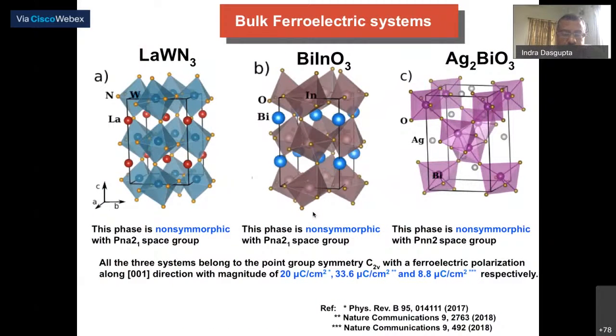Well, what we have done is essentially consider 3 theoretically predicted ferroelectric systems. They have a perovskite-like structure, but one of the key ingredients of the symmetry is that all these 3 systems are non-symmorphic, because there has been an argument in the literature that non-symmorphic systems can give you a large Rashba or large Dresselhaus splitting. So we chose that. The calculated ferroelectric polarization turns out to be 20 microcoulomb per centimeter square for this lanthanum tungsten nitride, 33.6 microcoulomb per centimeter square for bismuth indium oxide, and for Ag2BiO3, which also happens to be a charge order insulator, it turns out to be 8.8 microcoulomb per centimeter square.